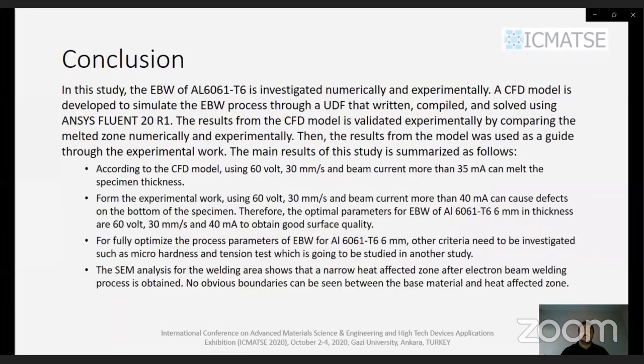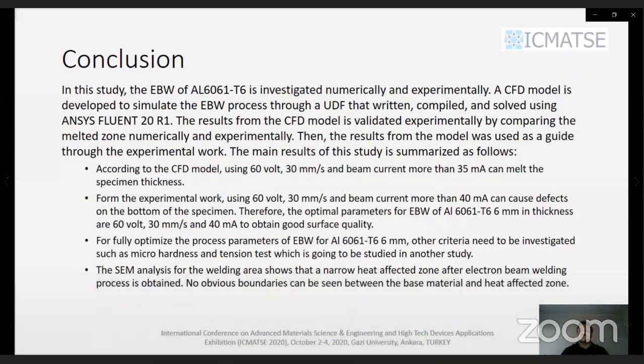In conclusion, in this study, the electron beam welding of aluminum 6061 T6 condition is investigated numerically and experimentally. A CFD model is developed to simulate the EBW process through a user-defined function that is written, compiled, and solved by ANSYS Fluent 20R1. The results from the CFD model are validated experimentally by comparing the melted zone numerically and experimentally. Then the results from the model were used as a guide through the experimental work. The main results of this study are summarized as follows.